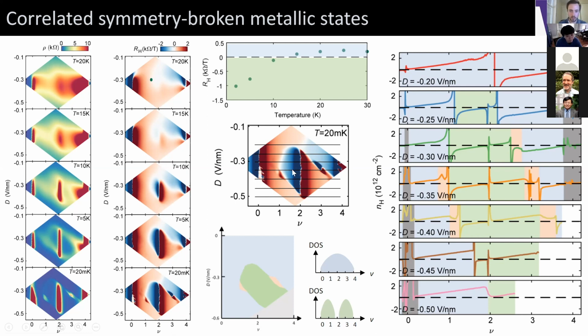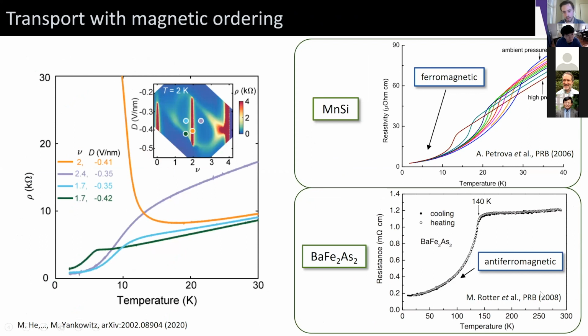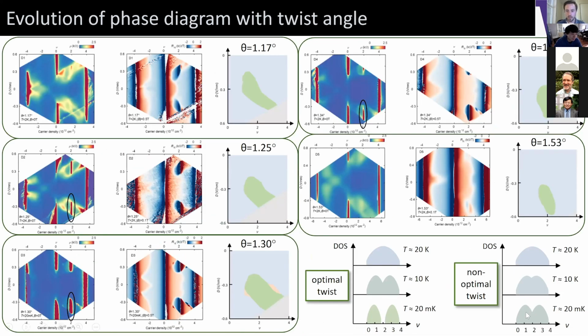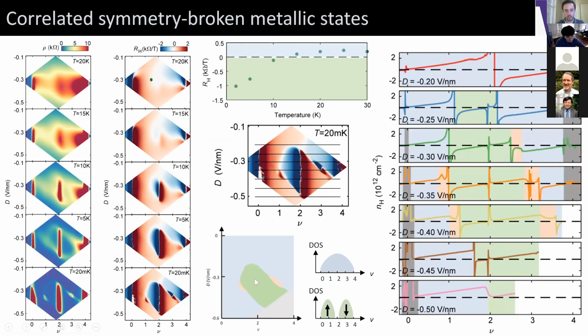It probably gets smaller, but we don't have a spectroscopic probe of that. But the basic idea is that even if you detune too far and you start closing the gap, you can still get some sort of symmetry breaking. The bands don't necessarily have to be fully gapped to have some sort of signatures of symmetry breaking. So the halo is basically a footprint of how far away you can move the chemical potential before you're simply too far away from half filling to continue spontaneously modifying these bands.